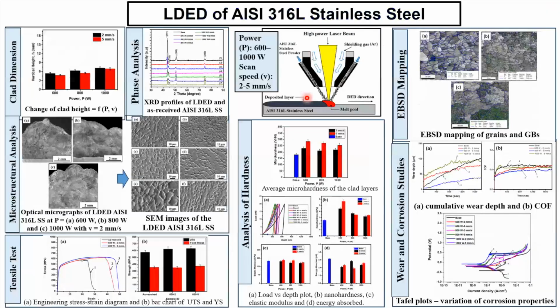And in the process, he was able to show that a very significant amount of grain refinement improves the mechanical properties, improves surface homogeneity, compositional homogeneity, and in the process also corrosion properties. So all this put together, one may argue that additive manufacturing products can actually offer you a better advantage than the conventional wrought products to some extent.